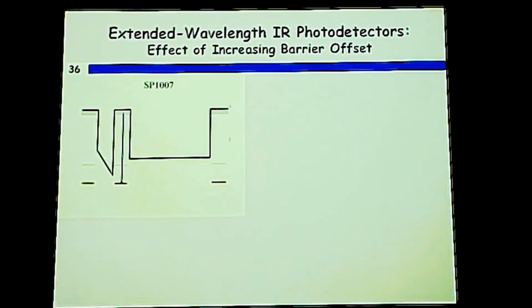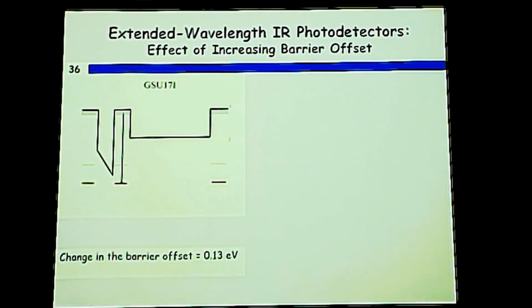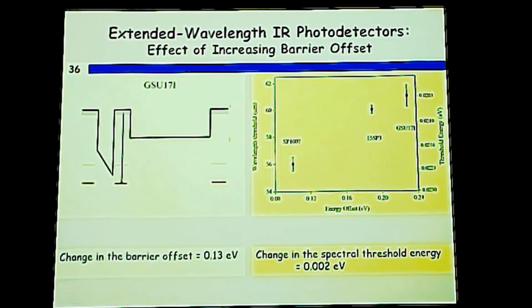In other words, what we changed in these 3 devices is the barrier offset, from the lowest offset to the highest offset. The change is 0.13 electron volt. The change in the threshold is 0.002 electron volt. We didn't see any proportional change in the threshold. So now the question is, what could be the mechanism? How did we get more or less similar threshold while we change offset like this?